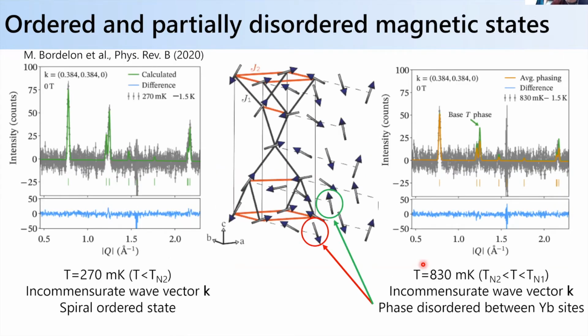So we did the neutron diffraction on this material, and we did it in the ordered state. So this is below TN2. So this is the ground state. And so at 270 millikelvin, the solution is actually an incommensurate magnetic structure.